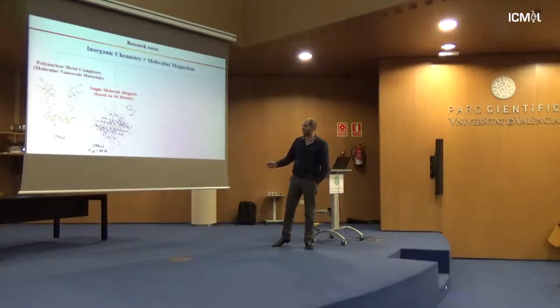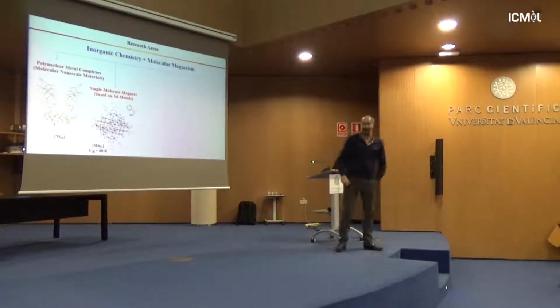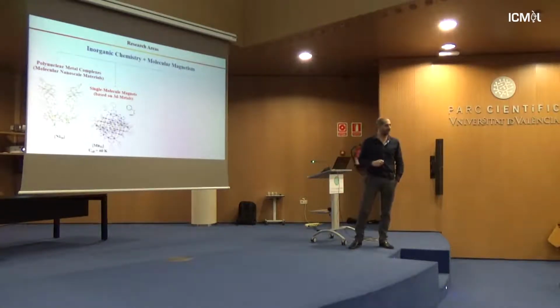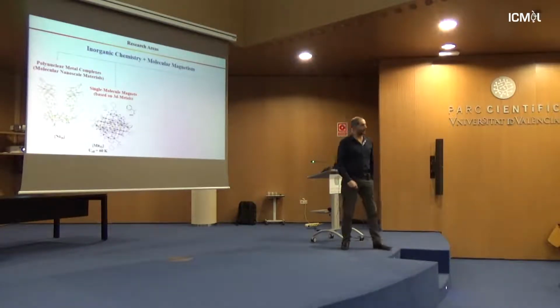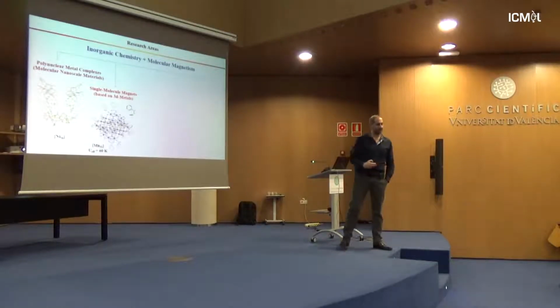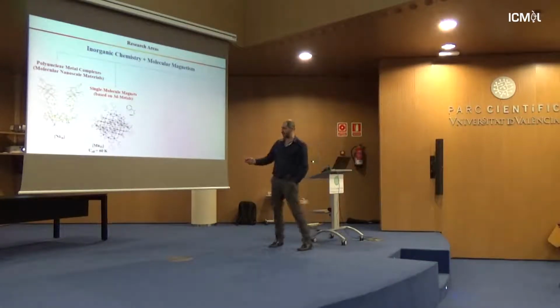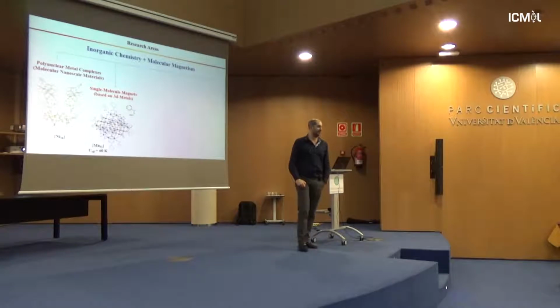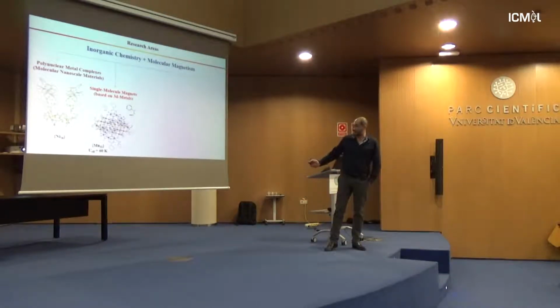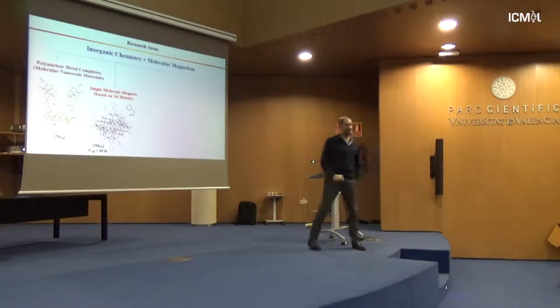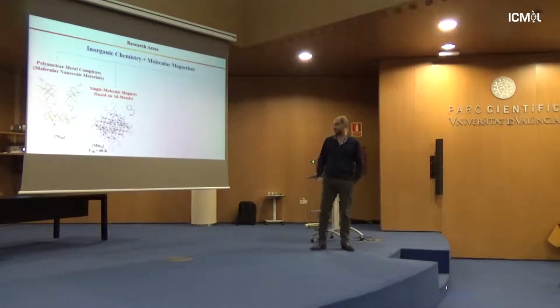Now, moving this field a little bit further, when you use the appropriate metal ion, like manganese, the trivalent manganese, which is anisotropic and has lots of unpaired electrons, and you're lucky, with the right combination of ligands, you stabilize cluster compounds, and hopefully you get nice magnetic properties, and particularly single molecule magnetic properties. And this is actually one of the few high nuclearity cluster compounds, actually the highest nuclearity compound with the largest energy barrier reported in the literature today.